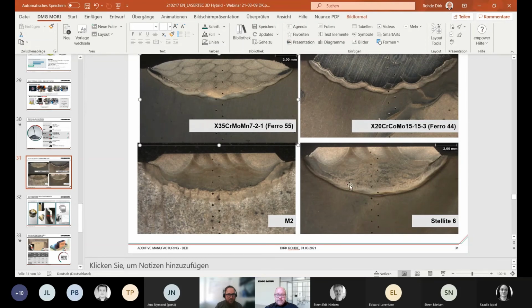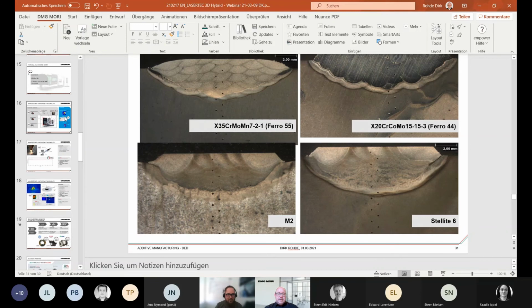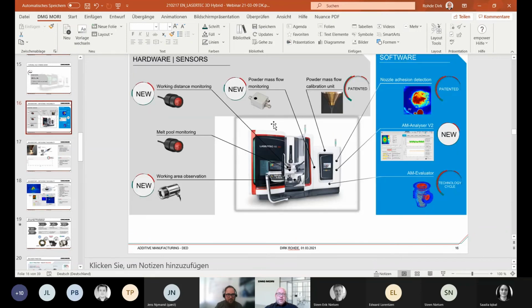And once the process has been figured out, you can throw one part after the other and really manufacture, coat, repair on an industrial basis. You don't need to care about any process parameter that might make it worse. What it can affect is what we try to prevent with our calibration, that we are sure that always enough powder is coming in, that the powder mass is correct, that we have the right nozzle distance to the part, and that the melt pool is